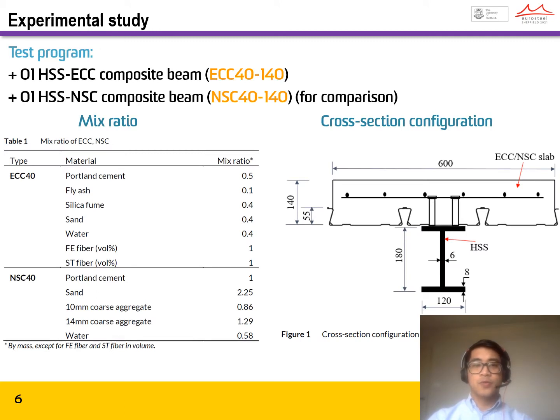Next, I'd like to move on to the experimental program. A total of two high-strength steel composite beams, one with ECC named ECC40-140 and one with normal strength concrete named NSC40-140, were cast, in which 40 denotes the targeted compressive strength of ECC or NSC in megapascals, while 140 indicates the slab thickness in millimeters. Both beams were constructed with identical cross-section configuration.